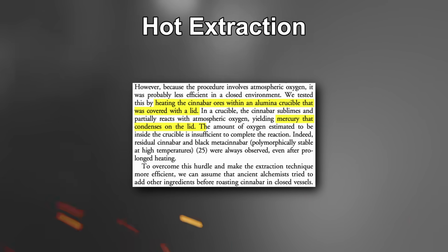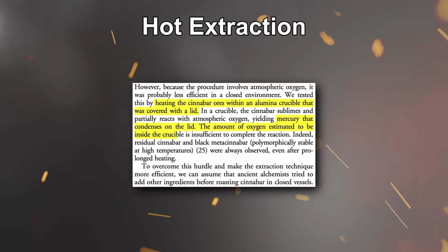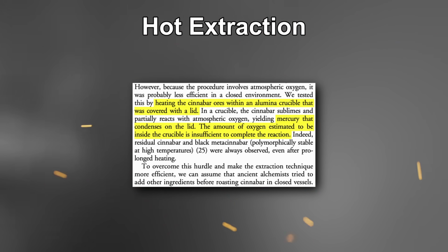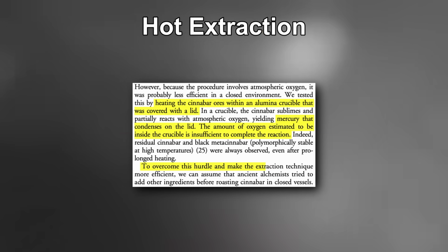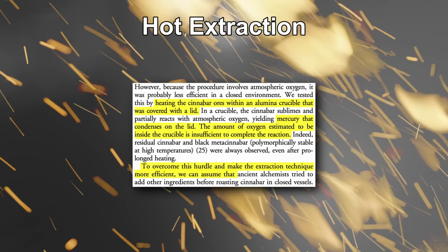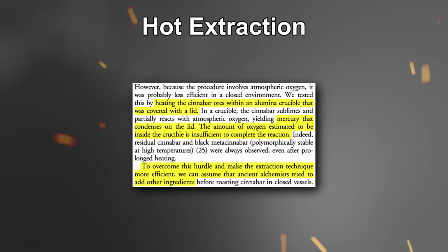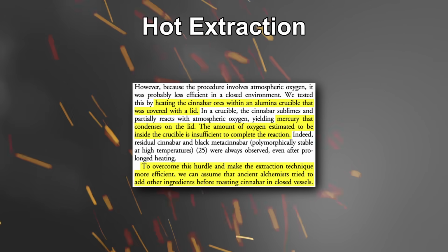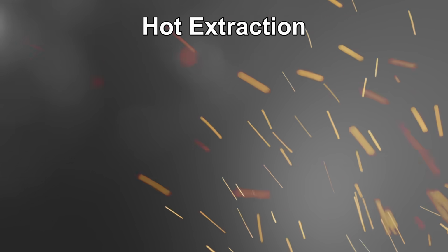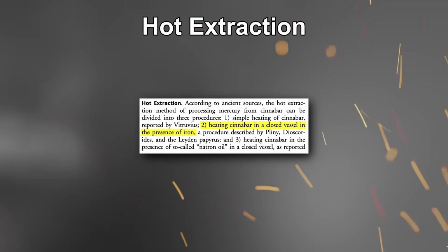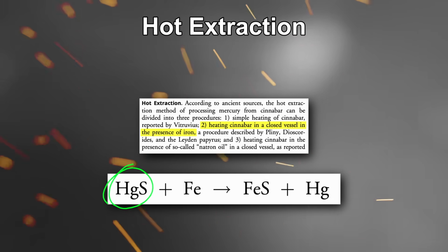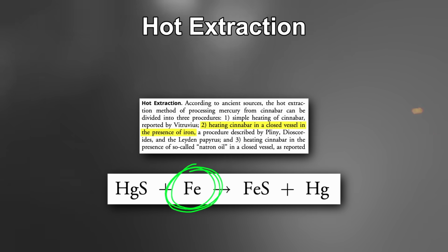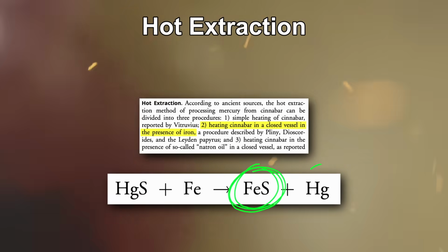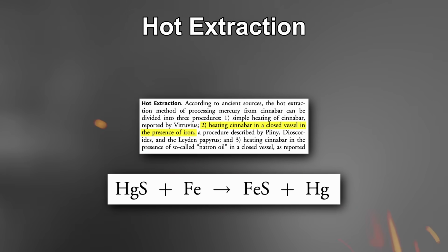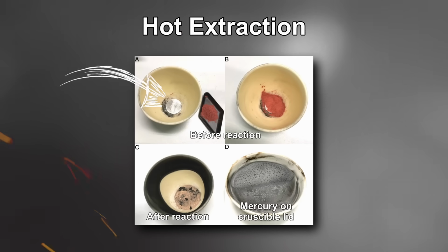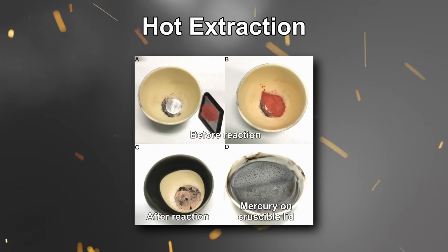However, they said that the amount of oxygen estimated to be inside the crucible is insufficient to complete the reaction. To overcome this hurdle and make the extraction technique more efficient, we can assume that ancient alchemists tried to add other ingredients before roasting cinnabar in closed vessels. This brings us on to the second hot extraction method: heating cinnabar in the presence of iron. In this case, the mercury sulfide would react solely with the iron and not with any oxygen, giving us iron sulfide and mercury. The researchers recreated this method by placing the cinnabar on a small iron plate within an alumina crucible that was then covered with a lid.